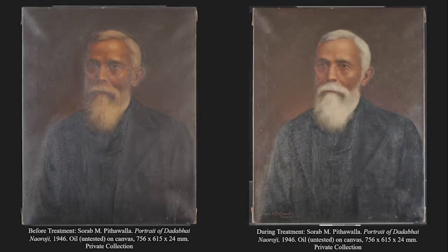So that broke up that top layer, and then we used a chelator, which was sodium tripolyphosphate, which is particularly good at chelating away metal ions, which are often found in surface dirt. It was also helpful in removing the greasy surface dirt because it's high pH, so it helps to saponify that dirt component. So that's what was used. Very interesting. Thank you very much.